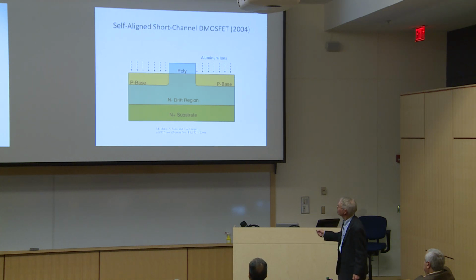Now the next step is we want to put in our N+ regions, and we want them to be very closely spaced to the edge of the P region. We don't want to have a mask alignment tolerance. So the trick here is we now thermally oxidize that polysilicon mask. We just put it in and heat it, and it converts the silicon to silicon dioxide. And when it does that, it expands by about, in this case, half a micron.